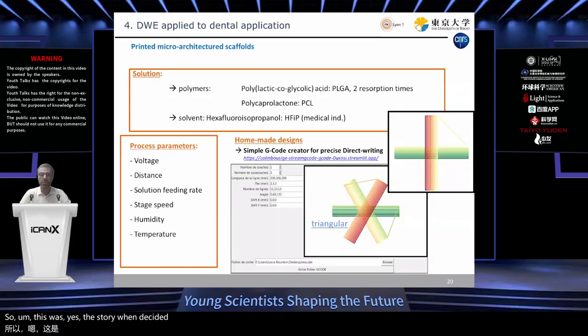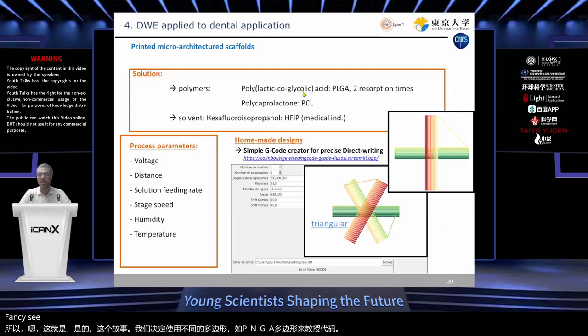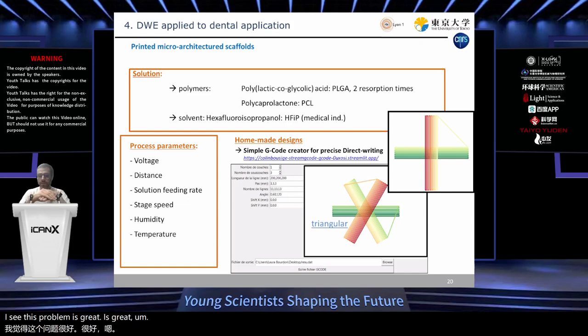We decided to work with different polymers like PLGA, polylactic glycolic acid. This polymer is quite nice because we can play on the resorption time depending on the ratio between the lactic and the glycolic parts. And we also wanted to use polycaprolactone because it's very interesting in terms of mechanical properties, even if the resorption time is longer than PLGA polymers. So we use an organic solvent to make the solutions.